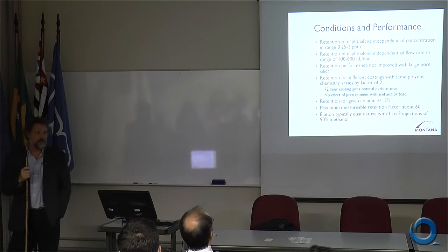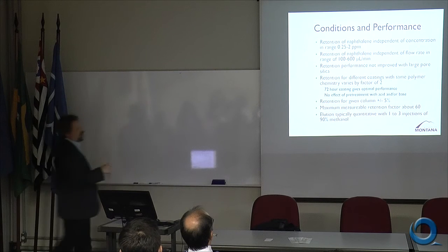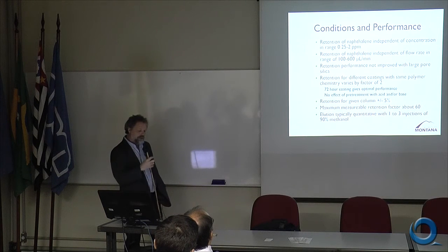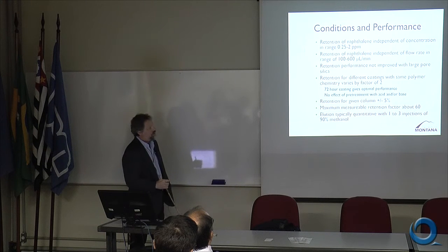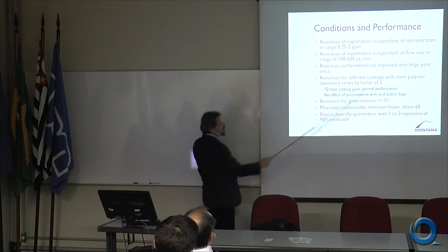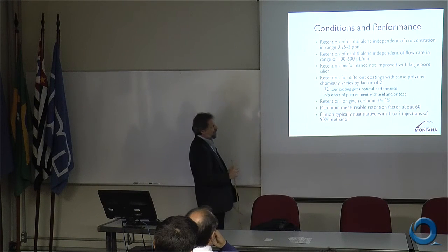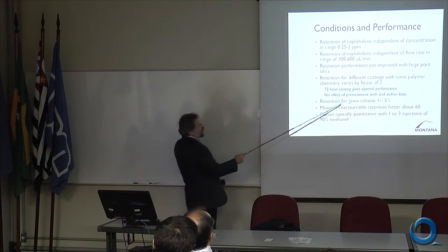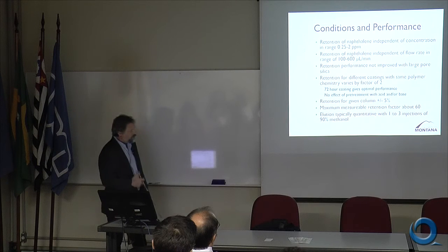If we coat different columns with the same nanoparticle chemistry, we don't get exactly the same response. We do get pretty reproducible response if we use this 72-hour coating, and we do get pretty much optimal performance for that particular nanoparticle when we use that coating. But we still see changes in retention factors of up to a factor of 2 between different coating procedures. And so this is something that would really have to be worked out before this could be considered a real viable approach. Retention, however, for a given column is actually quite reproducible. It's less than 5%.